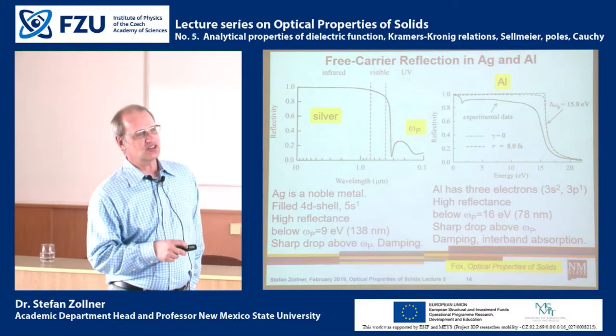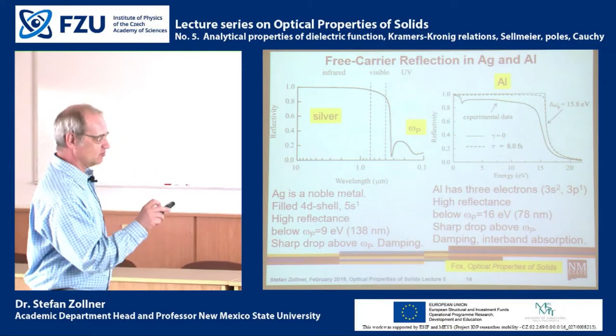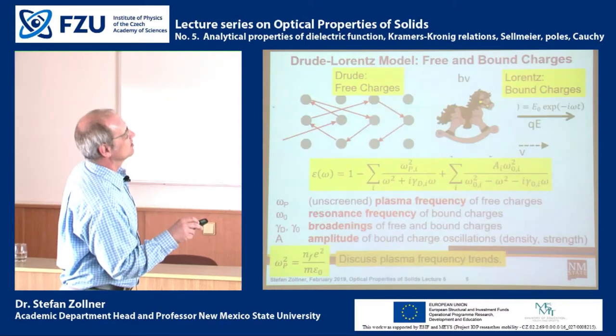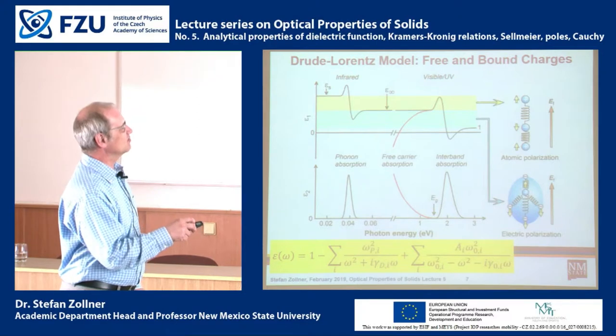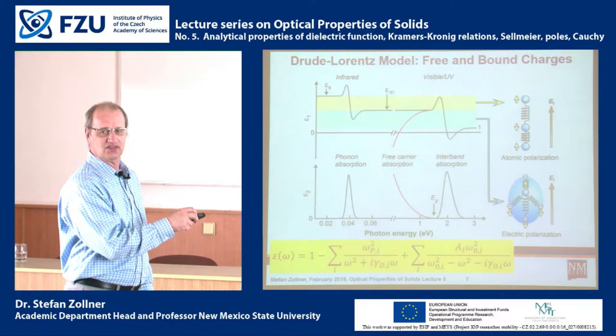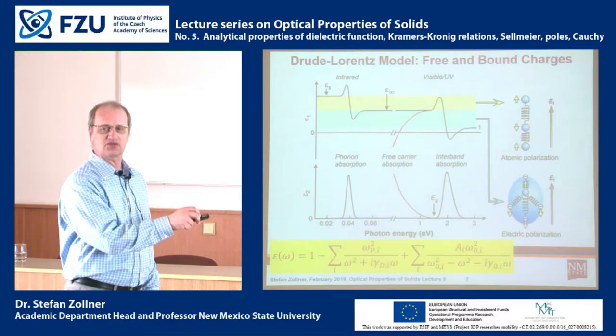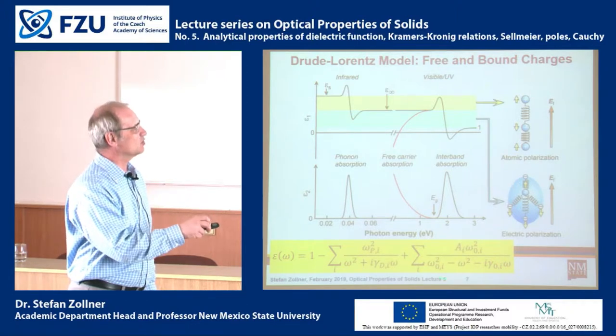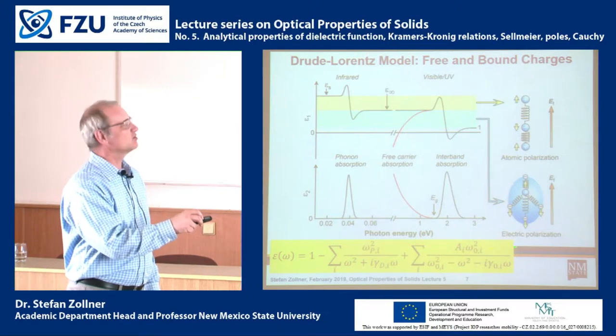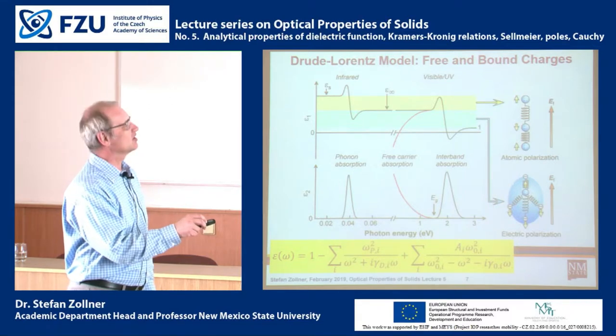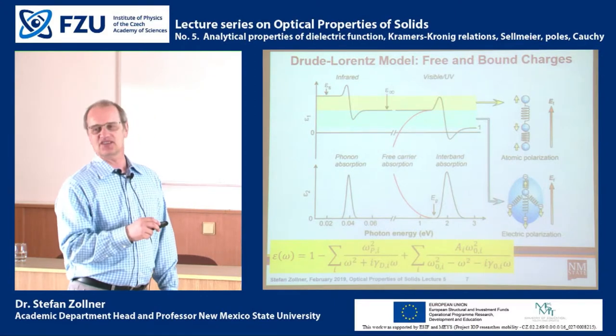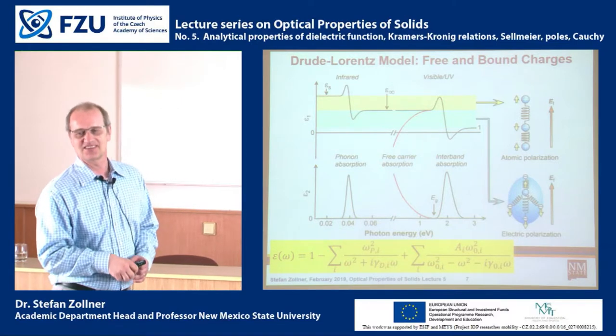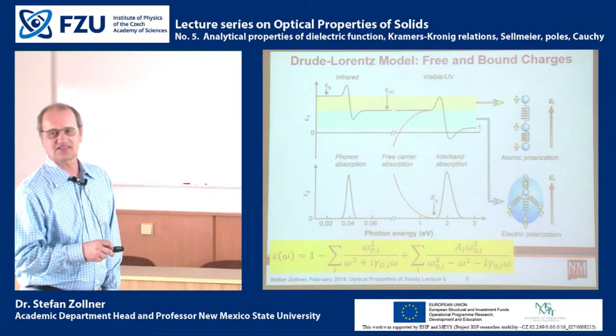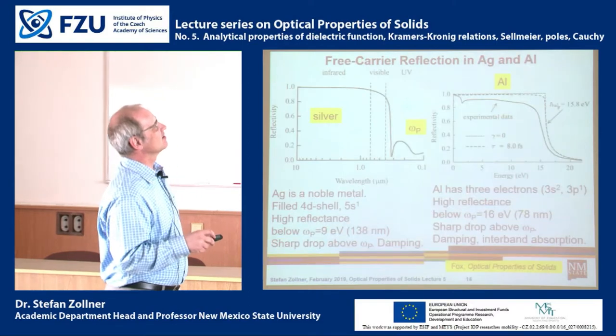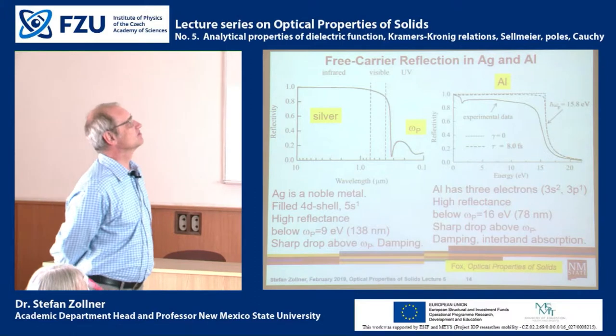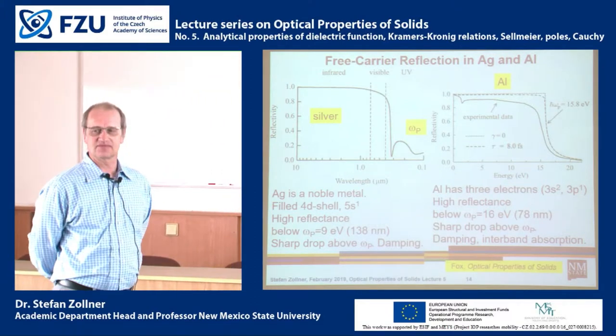And in order to answer your question, what one would have to do is go back to our Drude-Lorentz model. Here is the free carrier absorption for aluminum, which I can write down. And then here I can write down an expression for the absorption from that interband transition. And I can also write down an expression for the phonons in aluminum. And what we will see is that if we choose the correct broadening parameters, then we can see the interband absorption, but we cannot see the phonon in aluminum. I think that's the answer to your question. I mean, my argument is, if you have plasma, like in silver, with very small damping, then if you take the same oscillator interband excitation as in aluminum, it will be screened because of the low damping of the plasma.